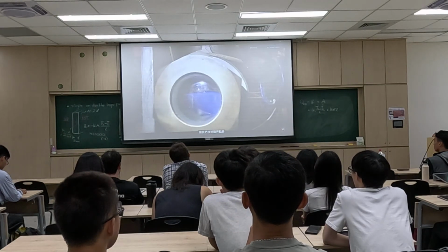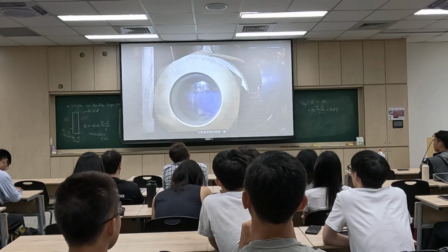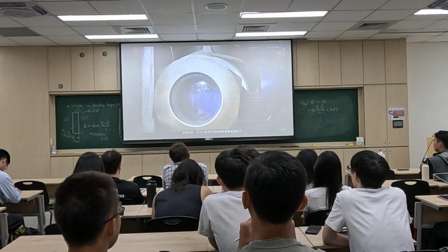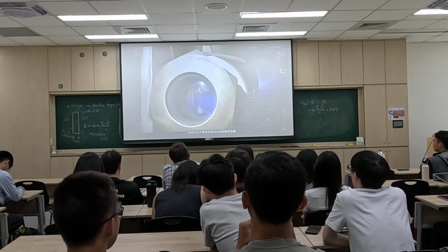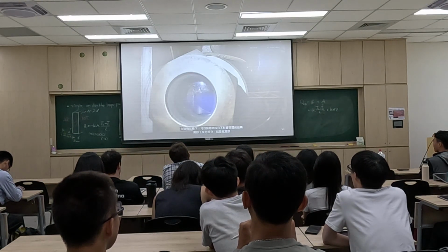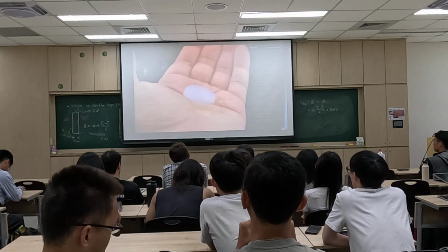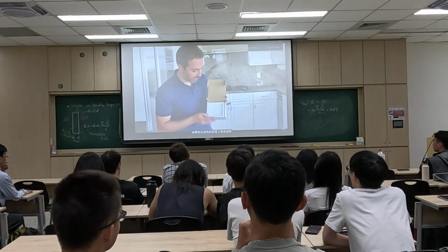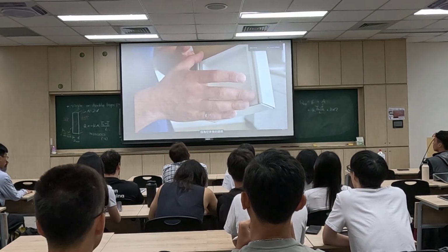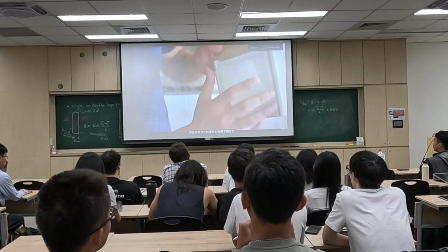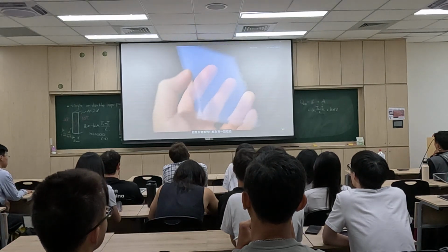As we approach the critical point, the surface of the liquid becomes kind of blurry. That is like weird waves. Yeah, I'll speed it up so you can watch the surface disappear altogether. You're now looking at the supercritical fluid of CO2. In this state, the CO2 can be vented without affecting the solid structure, and what you're left with is aerogel. If you look at aerogel on a light background, it's almost impossible to see because it is pretty transparent. But if you look at it on a dark background, then you can see that it has a slight bluish color.